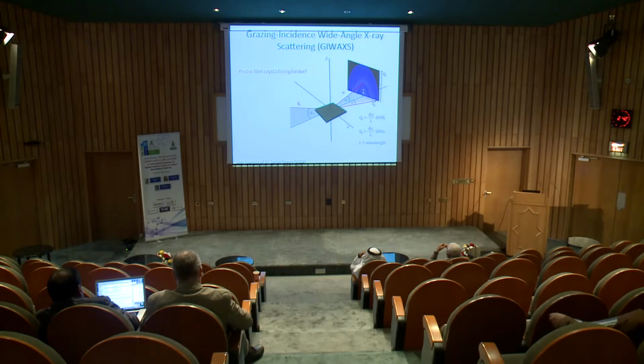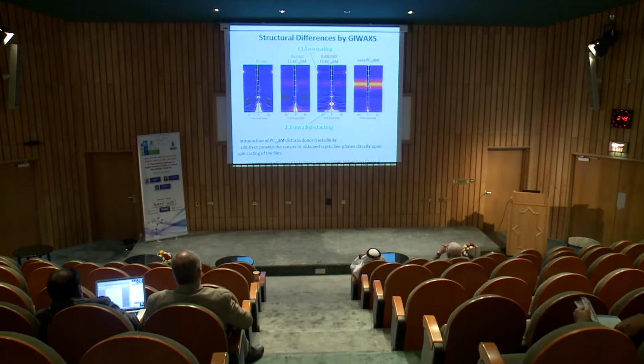The technique that we use to do this is called grazing incidence wide-angle X-ray scattering, short name GIWAXS. In this particular technique, you have your blend, the bulk heterojunction film. You shine X-ray at a very small angle, and you measure the scattering off the surface of your film. And so this technique really measures the degree of film crystallinity or film order in the blend. And so this is the result from GIWAXS.